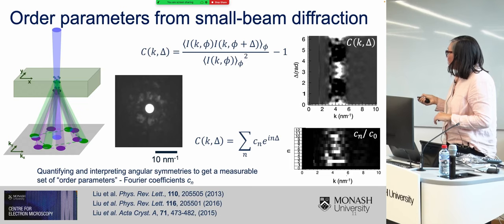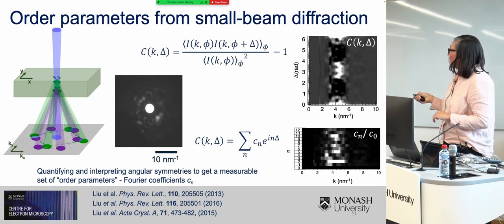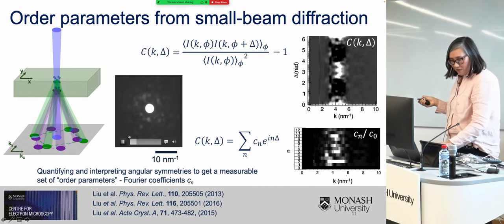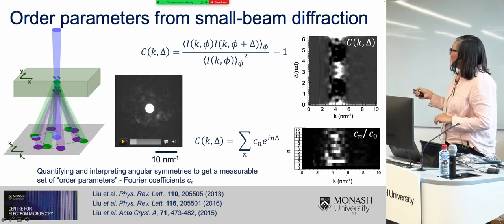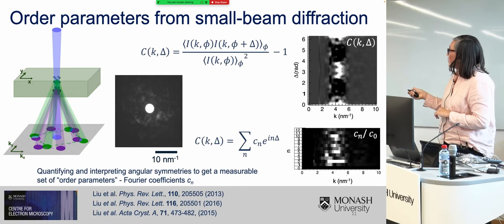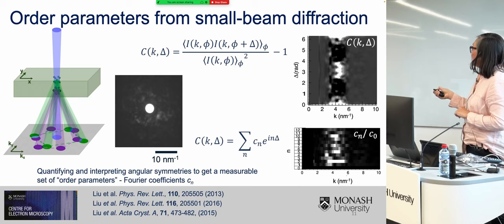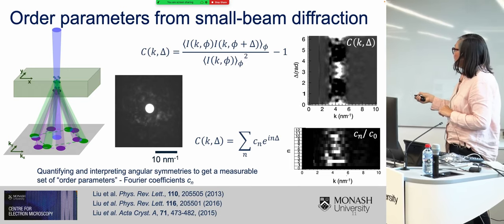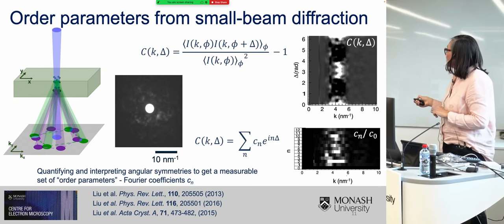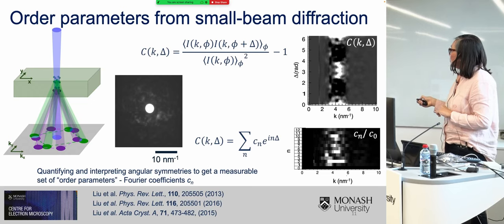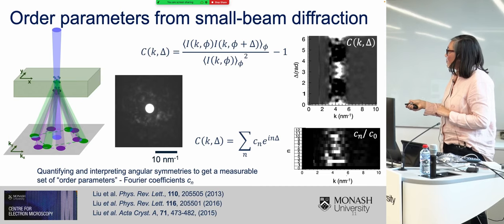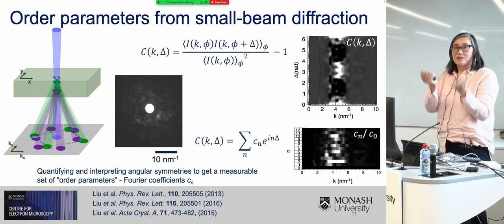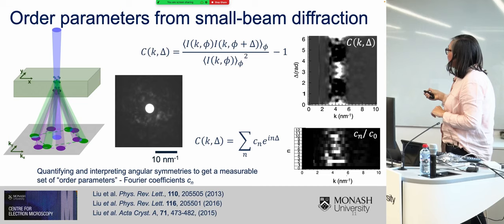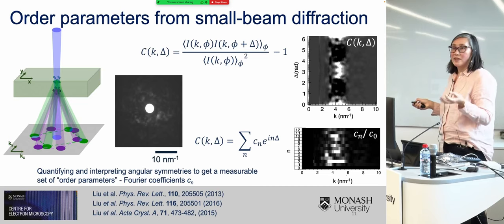To obtain some order parameters that I could measure from these diffraction patterns, I calculated this beast here, which is the angular order correlation function. The guts of this is that you take your diffraction pattern, you translate it by an angular increment delta, you multiply it by itself, and then you average this over all of your azimuthal angles. Here I'm showing this angular order correlation function as a function of delta, but also as a function of scattering vector k. You can see there's this band where we have a lot of prominent angular symmetries, which corresponds to the first sharp diffraction peak, which in real space is the first coordination shell. And it's intriguing that you can see so many different symmetries just from an individual pattern.